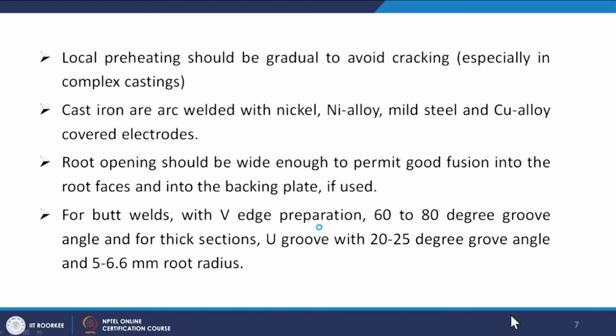Cast irons are welded with nickel and nickel alloys, mild steel, and copper alloy covered electrodes. The root opening should be wide enough to permit good fusion into the root face and into the backing plate, if used. For butt welding with V edge preparation, use a 60 to 80 degree groove angle, and for thicker sections, U grooves with a 20 to 25 degree groove angle and 5 to 6.6 mm root radius.